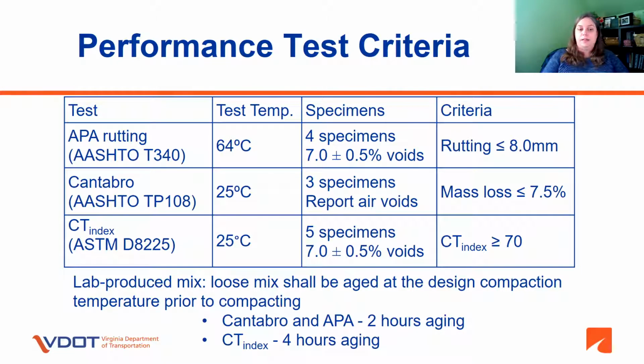The CT index test will be performed in accordance with ASTM D8225. This is again at a temperature of 25 degrees C. You'll be testing 5 specimens with an air void content of 7 plus or minus 0.5%. The CT index must be equal to or greater than 70. As you're doing mix design, lab-produced mix must be aged at the design compaction temperature prior to compacting. For the Cantabro and APA pills, this is 2 hours of aging. For pills tested for the CT index, it will involve 4 hours of aging.